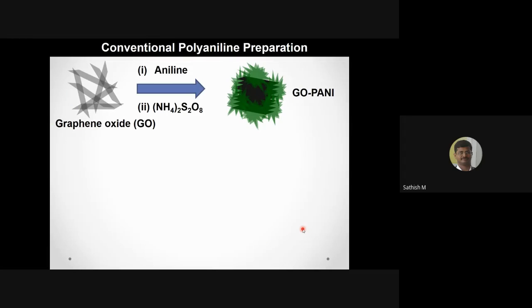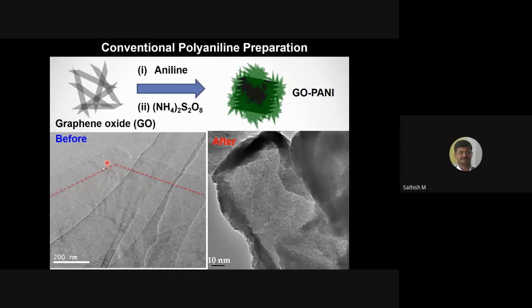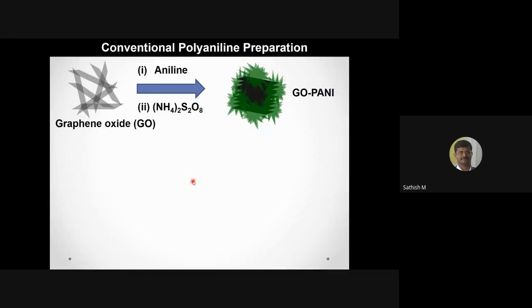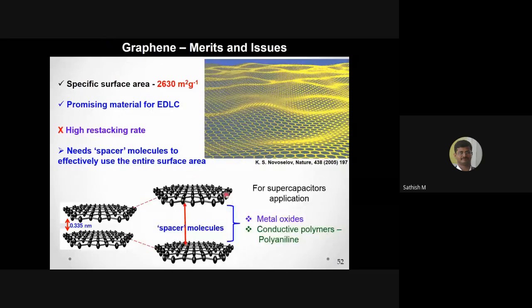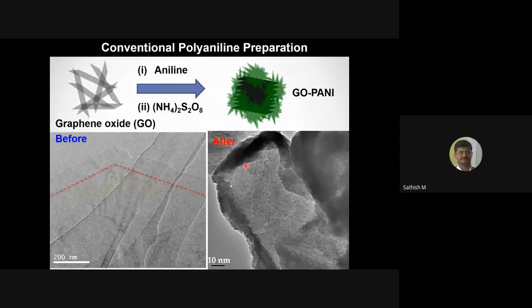So here is one of the interesting studies which we have done. Maybe I will just quickly go through it in another 5 minutes. You could see this graphene oxide. I simply put polyaniline. This is a TEM image of the sheet. It's a very transparent graphene oxide sheet. When I put polymer, there is a thick polymerization over the sheet. So the point of having EDLC from this sheet and pseudo-capacitance from this polymer has been destroyed, because you have a very thick polyaniline coating. So the graphene inside may not contribute to your EDLC capacitance.